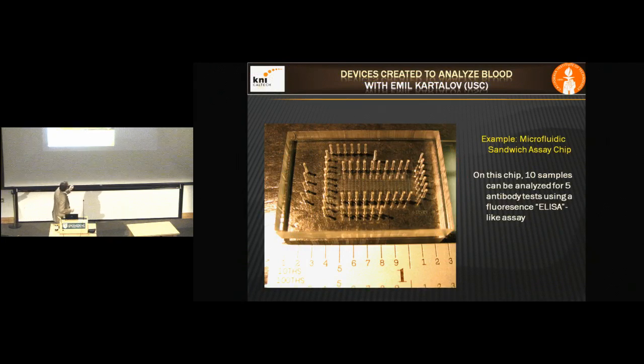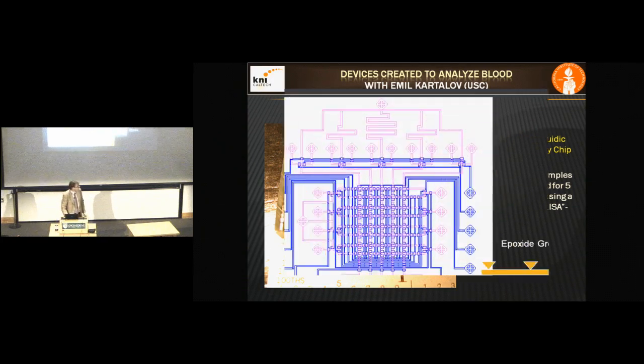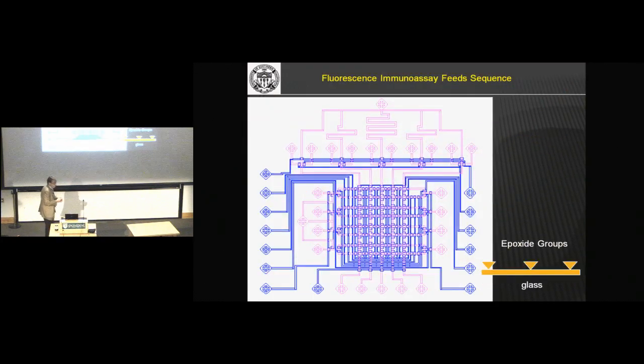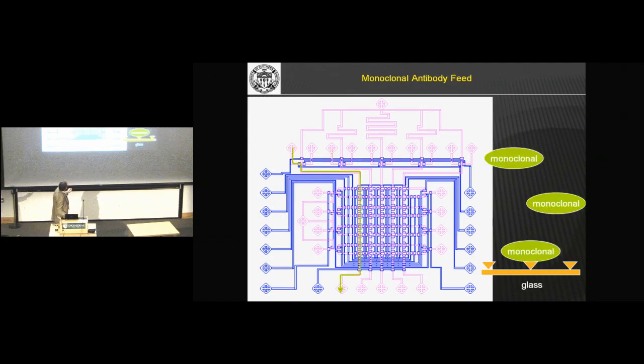So one of the systems is shown here. This system has about 600 or 700 valves on it. It's about 1.5 inches in dimension. And we basically can do tests based on moving around solutions. So we move solutions around pneumatically in this case. The pink lines here are the flow channels, and the blue lines are the control pneumatics that allow us to move solutions around.